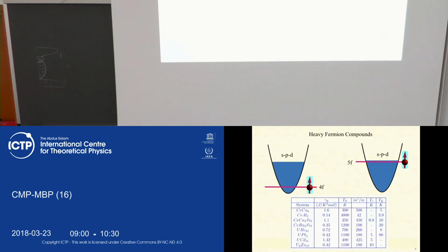So what you can see from this table is that the Fermi energy, first of all, is a few hundred Kelvin. The highest effective mass for these systems is in CeCu6, which is 500, but there are even systems with higher effective mass. But these are also a few hundred times the electron mass. To make a long story short, as I said, there are two families. One is cerium-based, another one is uranium-based.